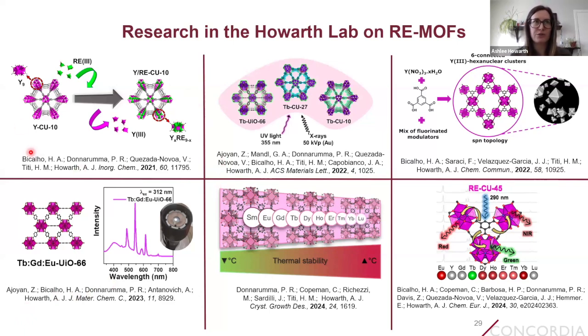So we've shown that you can do transmetallation in these materials, which means you can start with a yttrium-based MOF, put it in a solution with a new rare earth precursor, and end up with a daughter MOF that either has a mixed metal node or is completely transmetallated to a new metal. We've also studied the radioluminescence in some of these MOFs, meaning that we can excite these materials using X-rays and observe visible photoluminescence, which is of interest for X-ray detection applications.